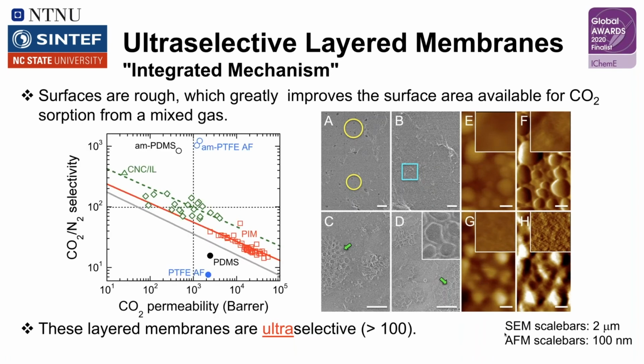And what we find is that if we start off with either the high permeability Teflon or PDMS, and we coat it appropriately, we can drive the selectivity up by almost 2 orders of magnitude. So now we're in this range for these types of materials. And if you compare that to the Robeson upper bound limit, you see that we're well above that, and even above the limit that was established for polymers of intrinsic microporosity, which was introduced last year. So we have highly selective materials. They're just slightly more selective than the cellulose materials that I showed you earlier.